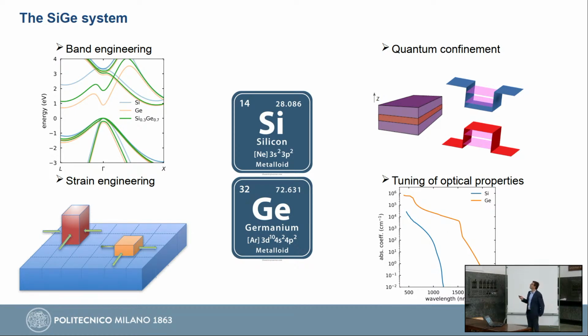Another thing that I can do with semiconductors, with silicon and germanium, is make a very thin layer of the order of tens of nanometers. And so I can confine electrons and holes in a small region where quantum confinement effects pop up, which are not visible in bulk material. And another thing that we can also change when we mix silicon and germanium is the optical properties.